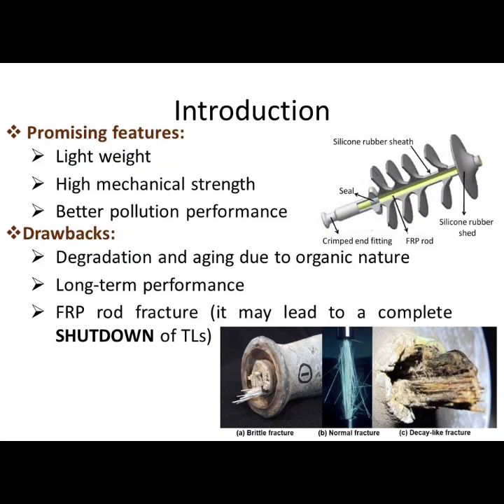However, a new type of the FRP rod fracture has been reported in many countries, which is known as the decay-like fracture. This new type of fracture is mainly due to the degradation of the epoxy resin matrix under the action of the electrical discharges and also due to the water and acid penetration through the silicone rubber housing.